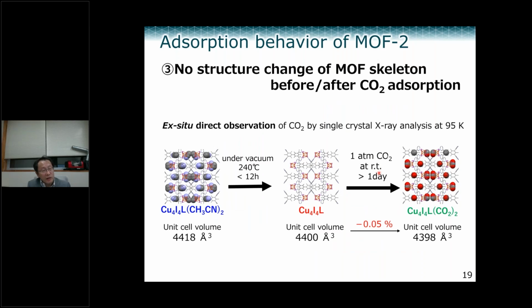First, we checked the crystal structure to investigate what's going on here. This network has acetonitrile as a guest. In this case, the unit cell volume is 4,418 cubic angstrom. If you put this crystal under vacuum at 240 degrees for over 12 hours, you can remove the acetonitrile very nicely. Then we collected the data of this empty cage at 95 Kelvin and observed the structure very nicely. The unit cell volume became a little bit smaller, now 4,400 cubic angstrom.